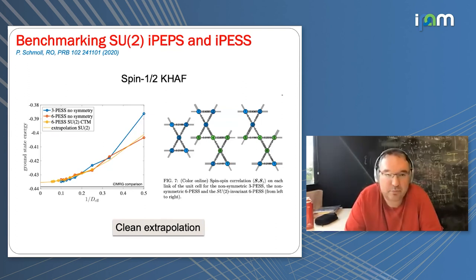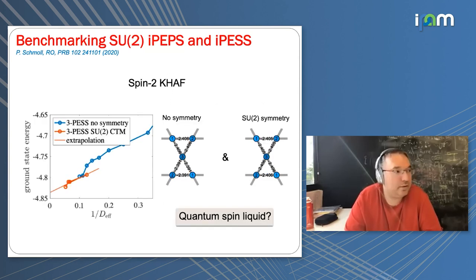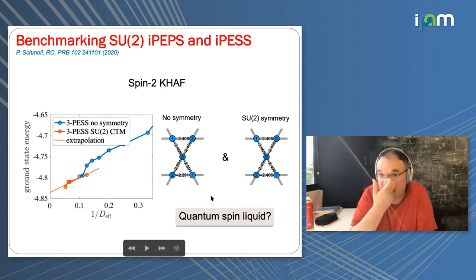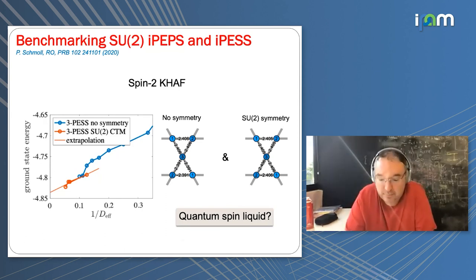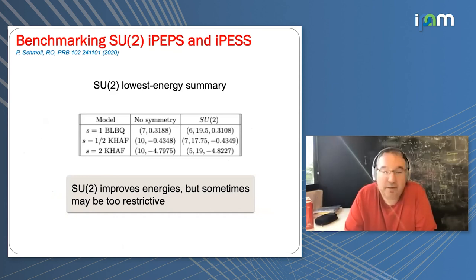We did the same simulations for the spin 1/2 Kagome Heisenberg antiferromagnet. We obtained nice calculations with a clean extrapolation. Here, the purpose was just to check that it is working and everything is compatible also with a quantum spin liquid. And also for the spin 2 Kagome Heisenberg antiferromagnet, for which surprisingly we didn't find any previous work, we were able to reach very large bond dimensions, but still clearly one needs larger to reach convergence. And our results seem compatible with a quantum spin liquid, but since we didn't reach convergence, we cannot claim anything. Now, this is a summary of the lowest energies that we found.